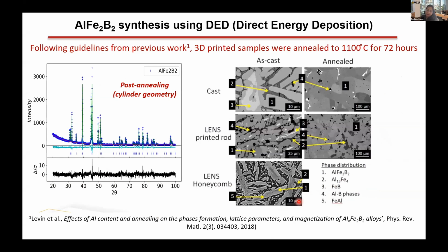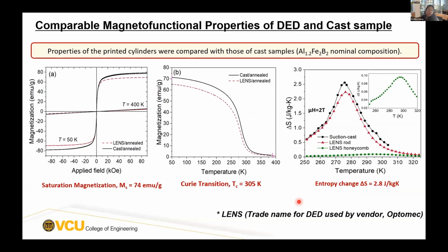Commensurate with our results for the microstructure, we noticed that the 3D printed cylinders also showed good magnetization properties comparable to cast material: an M-sub-S of 74 EMUs per gram, TC of 305 Kelvin, and comparable delta S. But we completely lost the delta S in the honeycomb samples.